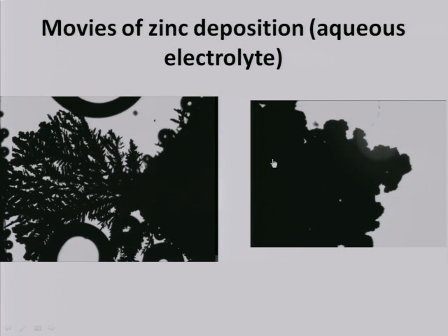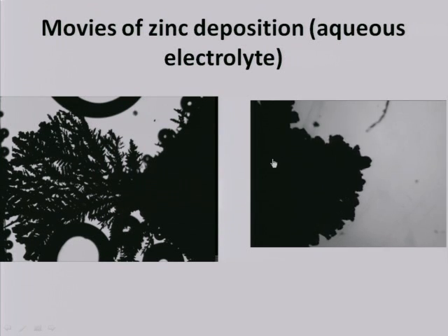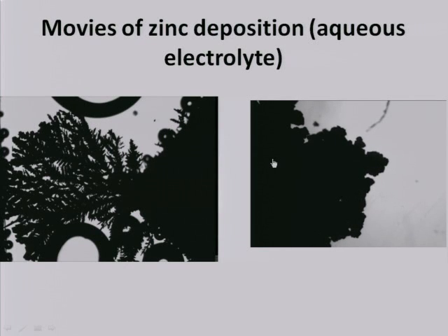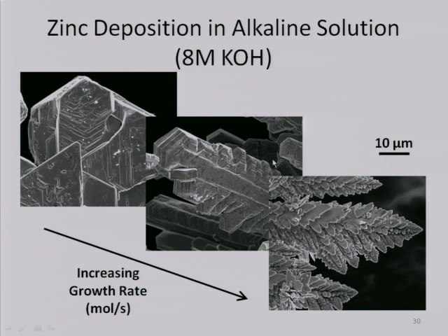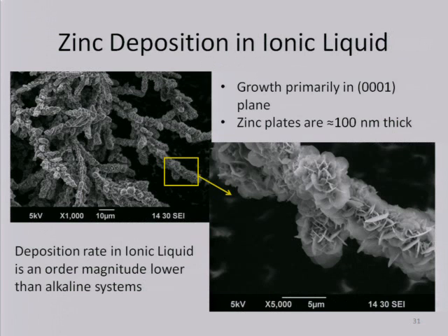Let me try something different. There we go. So, here are some micrographs from our lab. This is zinc deposited at low currents. As we go to higher currents, it becomes more irregular, and at the very highest currents, we develop these nasty dendrites. So we're spending quite a bit of effort looking at the microstructure of the zinc that is deposited when we work with these various electrolytes.